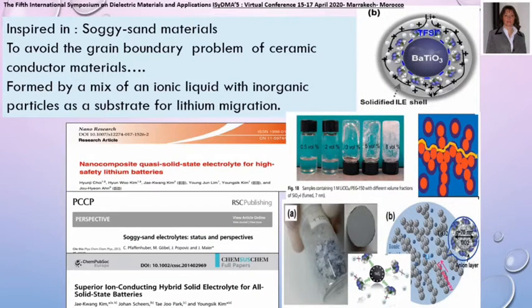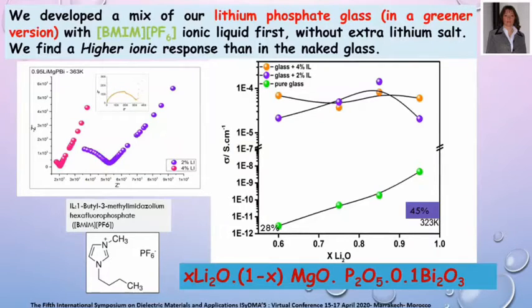Now, inspired by soggy-sand materials, which were created to avoid or to diminish the grain boundary problem of ceramic conductors, and were designed by the combination of inorganic particles with ionic liquids that confer a favorable path for ionic migration over the crystalline surfaces, we developed our hybrid glass. Our hybrid glass is formed by the combination of an improved version of our phosphate glass, where the barium oxide was replaced by magnesium oxide to obtain a lighter and greener glass, with the ionic liquid [BMIM][PF6] that has a high viscosity. We obtain a very good solid electrolyte.